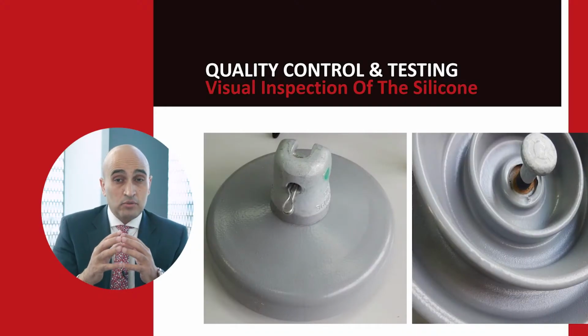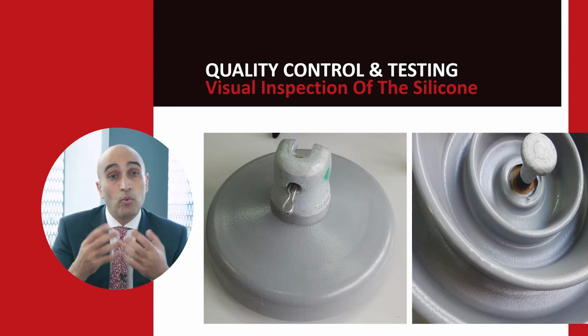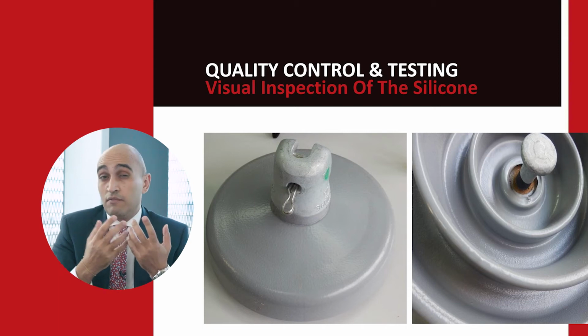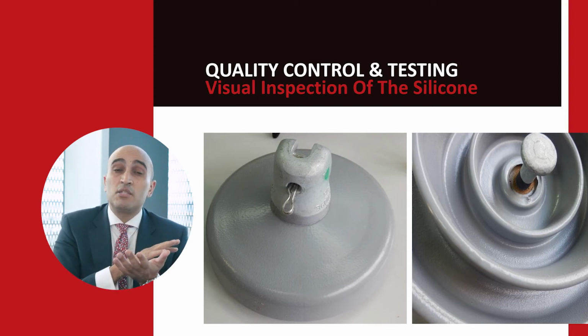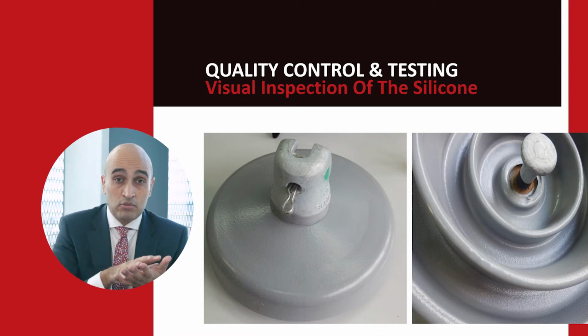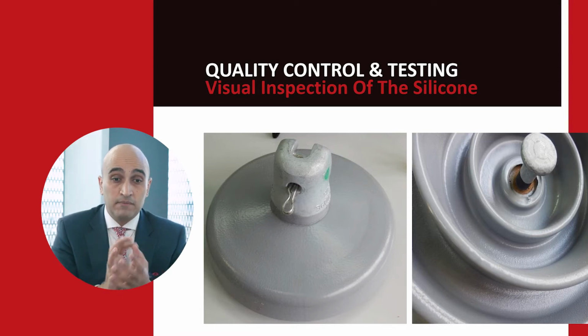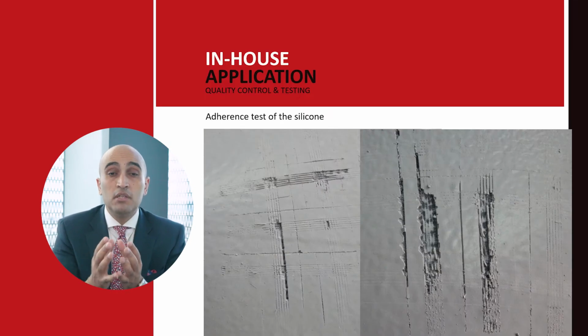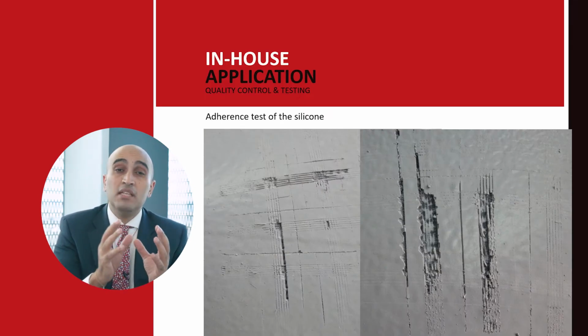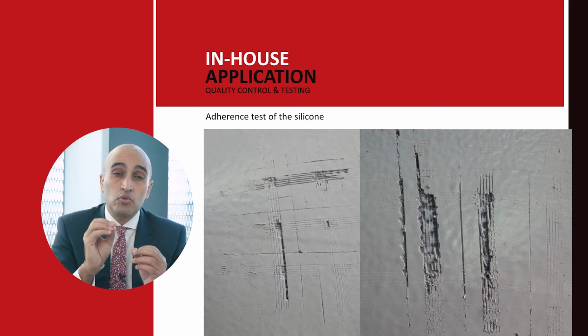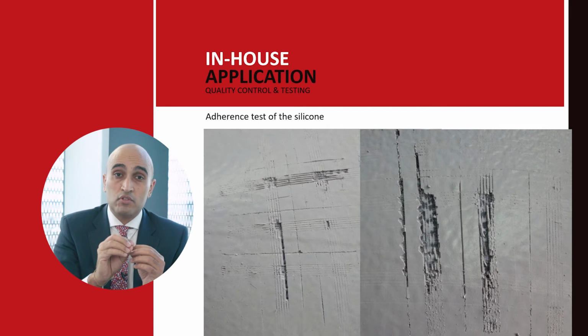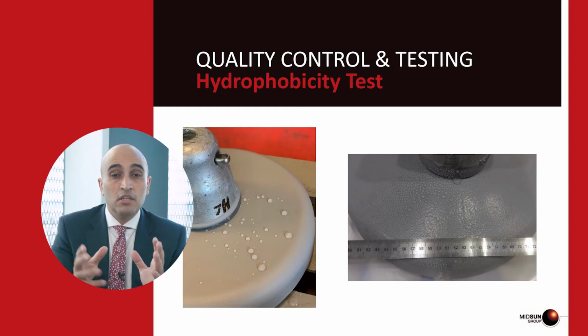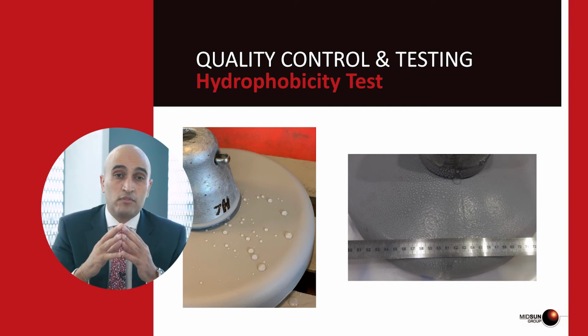After the application of the RTV coating, and when it's cured, we need to proceed to a quality control of the application. The first is visual inspection. We need to make sure that the coating is applied throughout the whole surface of the insulators. There is no white spot, there is no uncoated area. That's an important thing. Second, we need to perform a test randomly on some insulators to make sure that the adherence of the coating to the surface of the insulator is correct. Third, we recommend to test the hydrophobicity of the RTV coating. It's a very simple method, we only have to spray water and check the angle of the droplet of water on the surface of the insulator.